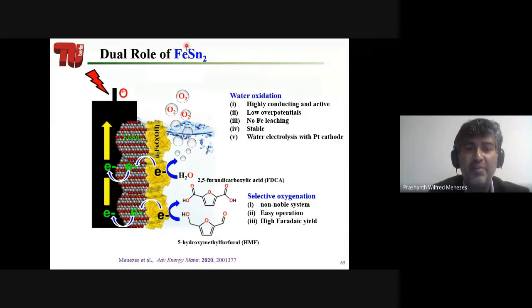We also use other intermetallics such as iron tin 2, and we show that we can produce a lot of oxygen evolution reaction. And this is the first time we also used this material for organic oxidation. So we took HMF, 5-hydroxymethyl furfural. It's a very important substrate in polymer chemistry. And then we oxidize this thing with oxygen, molecular oxygen, under this electrochemical condition to form FDCA, 2,5-furandicarboxylic acid, which is a very important or valuable chemical in polymer industry, as I said.